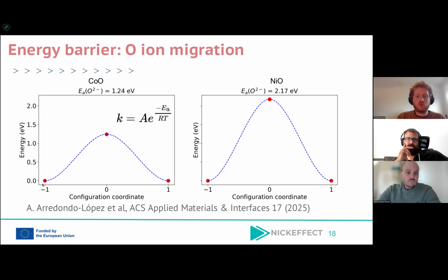And so you see that to go from one to the other, the vacancy has to go through a higher energy state. And so it has to go through an energy barrier. That's what we call the activation energy in an Arrhenius law like this. And so the results are there. You see that the activation energy in cobalt oxide is 1.2 eV, and in nickel oxide is 2.2 eV.